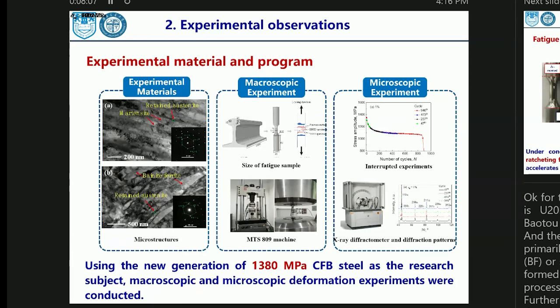And for the macro experiment, we used the MTS machines to do some tensile and compression, and also some multi-axial loading paths. To investigate the evolution of the microstructure phase during the process, we conducted XRD experiments at different numbers of cycles of the interrupted experiments, which can further give us the volume fraction of the retained austenite and the dislocation density.